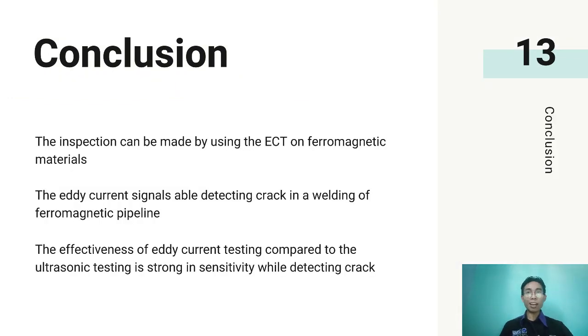Okay, as a conclusion, throughout all the observed and proven results, it shows that the weldment inspection can be made by using the ECT on ferromagnetic material. Next, the eddy current signal is able to detect crack in a welding of ferromagnetic pipeline. Although the UT inspection is very accurate, it needs a lot more focus, because the movement while inspection is in process is quite large and slow. And next, the effectiveness of eddy current testing compared to the ultrasonic testing is strong in sensitivity while detecting the crack in the welding.